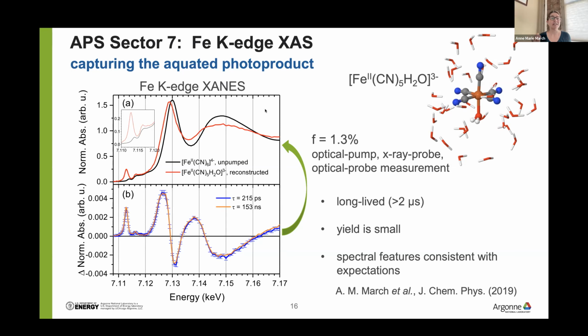Our laser-pumped signal, you can't see a difference from the ground state plot in the top figure. So we look at the difference signal, and we do in fact see a very, very nice difference spectrum after pumping. I have 2 time delays there. We see it at 215 picoseconds, and then we see it hasn't changed at all out at 153 nanoseconds. And so we thought, oh, cool, this must be the signature of the aquated product.